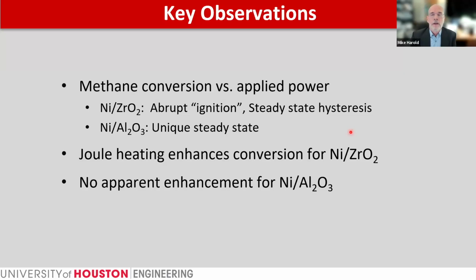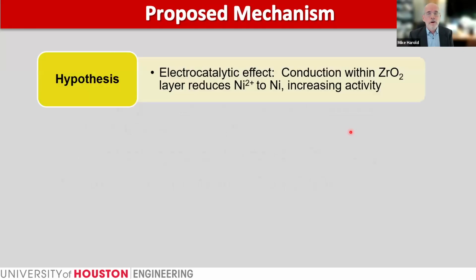So really, what's going on here? We have multiple steady states, not expected for an endothermic reaction. We have an important effect of the catalyst support. We have no apparent activity of a wire that does not have nickel as part of the coating. And again, there's a notable difference between the catalyst support on which the nickel is impregnated. So what's going on? Well, that's going to lead us to a mechanism, and we've considered several mechanisms. This one, we believe, checks all the boxes, but it's definitely up for debate. So let me walk you through our hypothesis.